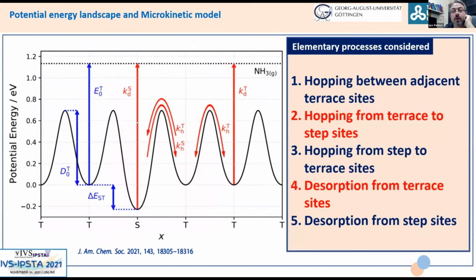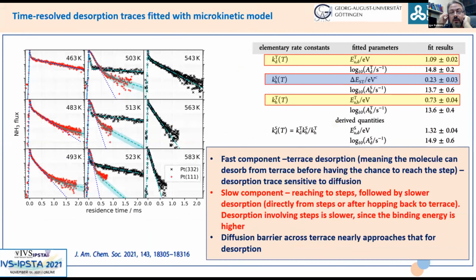First of all, hopping between adjacent terrace sites, hopping from terrace to step sites and vice versa, desorption from terraces and desorption from steps. Now, while doing this fit, we are getting some kinetic parameters, which already teach us a lot, right? In the form of the Arrhenius equation, this is the log of the prefactor, and these are the activation energies. So first of all, we learn that the fast component belongs to terrace desorption.